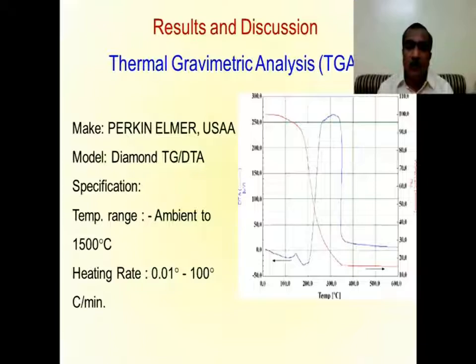Once this cobalt ferrite nanoparticle was prepared, it was subjected to thermal analysis, thermogravimetric analysis, and through this study we obtained the ferritization temperature. Once this ferritization temperature is achieved, we sinter the nanoparticle at that particular temperature and use it for further study.